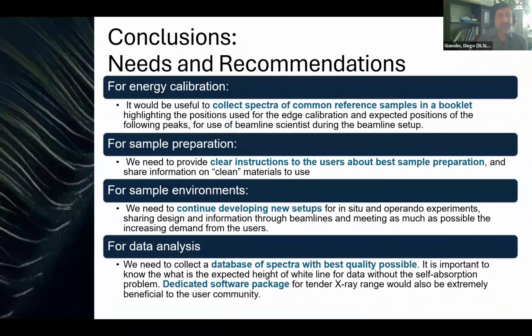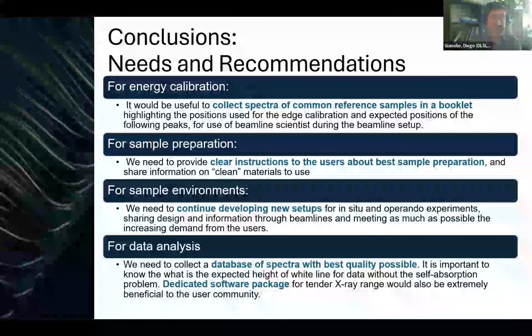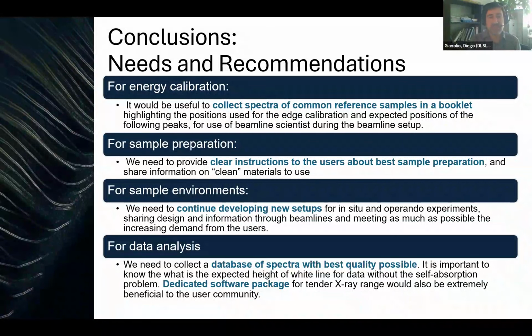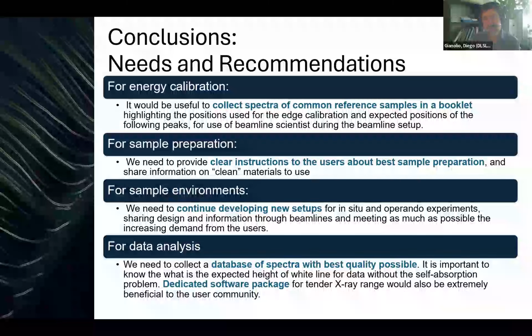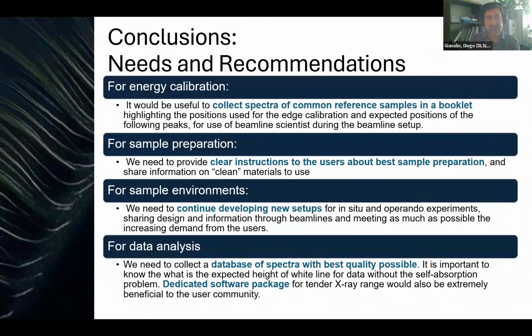So, reaching the final slide, I would say to try and draw some summary in conclusion. For the energy calibration, we think that what would be really useful would be to have a specific booklet for tender X-rays where we collect as many spectra as possible of common reference samples, where we don't only have the position of the edge that can be used for calibration, but also the position of the following peaks, for example.